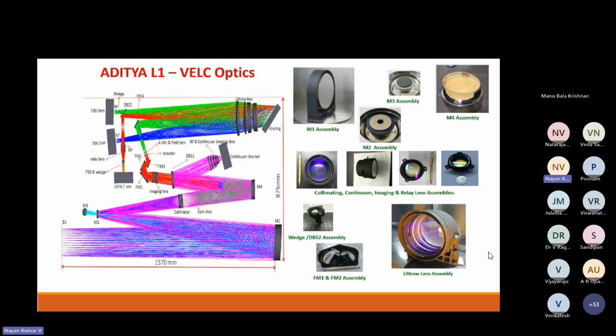Basically it undergoes a full-level mechanical analysis, FEM based, and then in the actual thing itself we develop a model and subject it to vibrations and temperature escalations. So it undergoes all the endurance tests, and then we ensure that no disturbance happens in the optical alignment. We also had a stainless steel mirror, which had an elliptical hole drilled in it, and still the surface figure has to be retained. It's a real challenge.